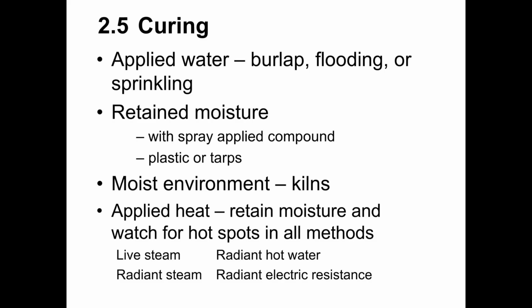We can also retain the moisture that's inherent within the concrete. We can do that by spraying on the unformed surface a moisture retardant. More commonly, instead of spraying a moisture retardant, we're going to use a plastic sheet or a tarp to cover that surface and help to retain the moisture that is naturally evaporating from the concrete surface itself. We can also create a moist environment by using a kiln. Kilns were more common for some types of products that we don't see produced a whole lot anymore.